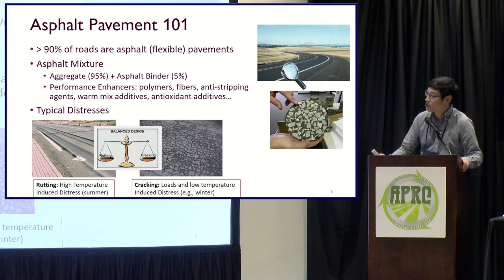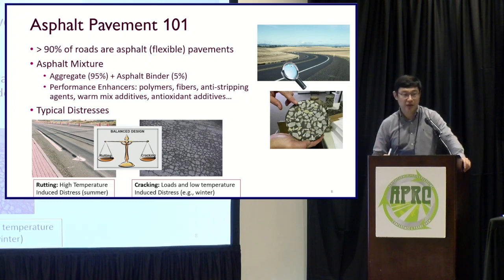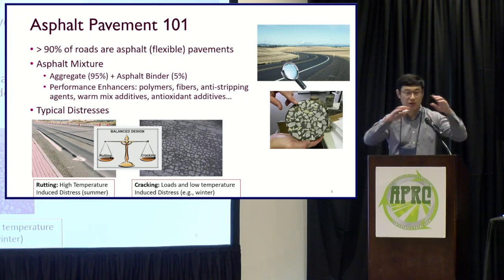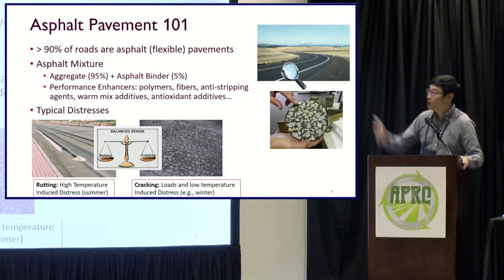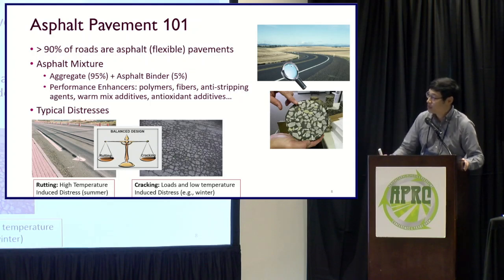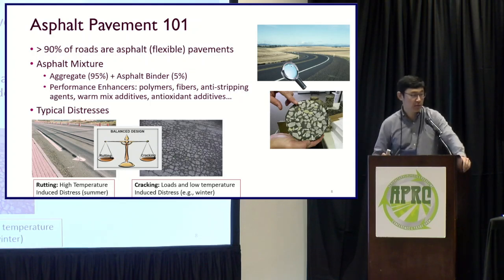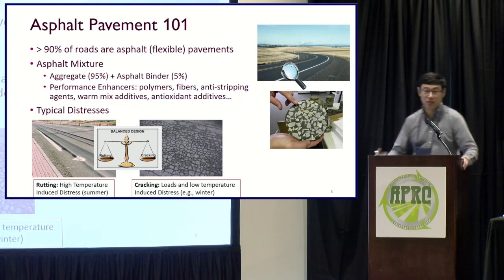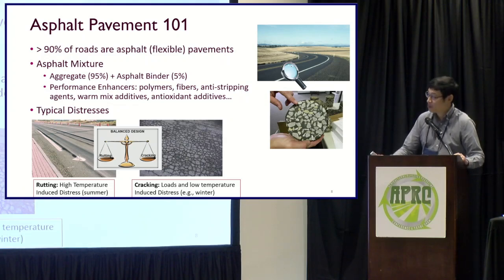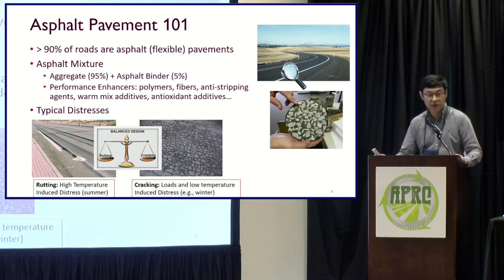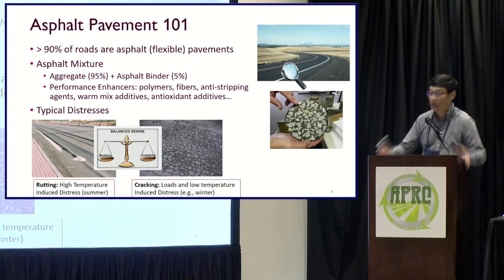Well, for the asphalt mixtures, roughly, if you look closely here, in the asphalt mixture we have about 95% by weight aggregate. Big rock, small rock, they form the skeleton of the mixture, and we put roughly 5% asphalt binder to bond the aggregate together. And then we have some performance enhancers. We use a polymer in it, SBS, SBR, and definitely plastic is a polymer, so we can use it as a polymer modified asphalt to improve the performance. We add fibers to improve the ductility of the mixture and reduce the cracking.